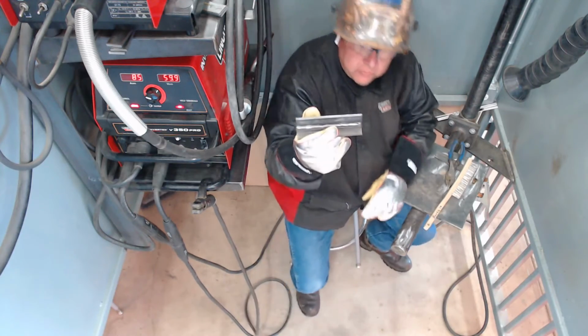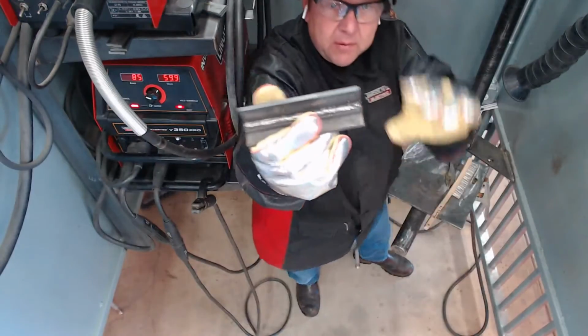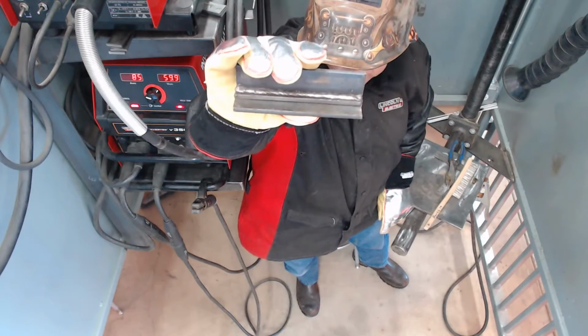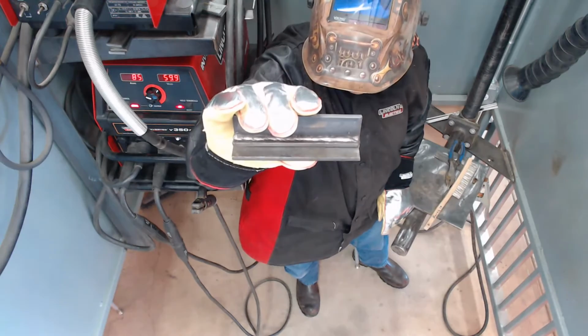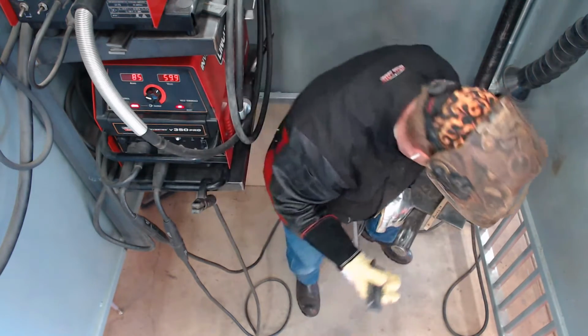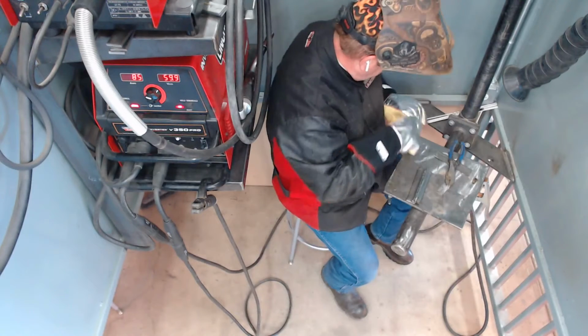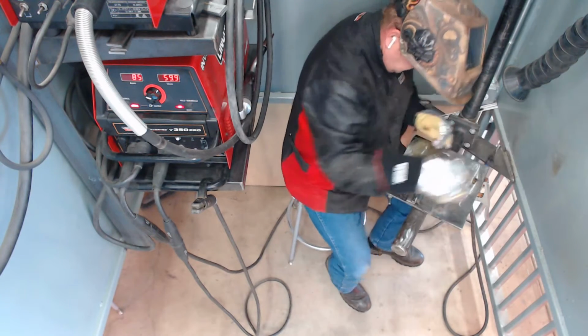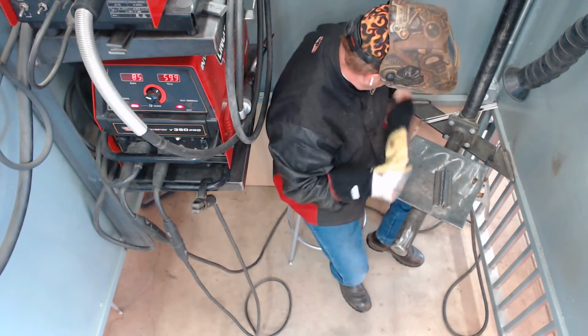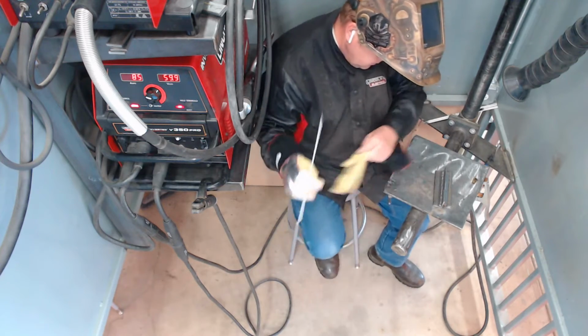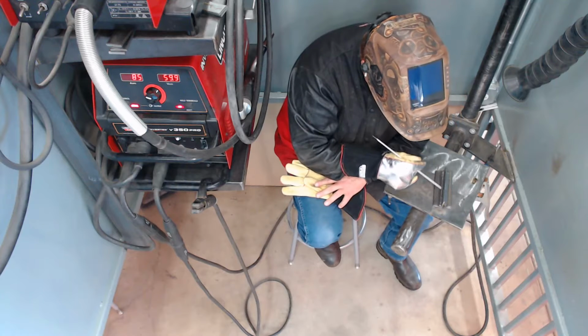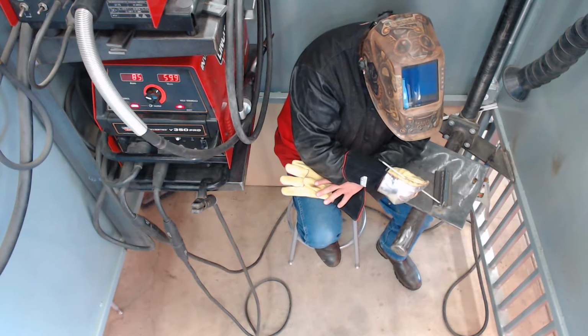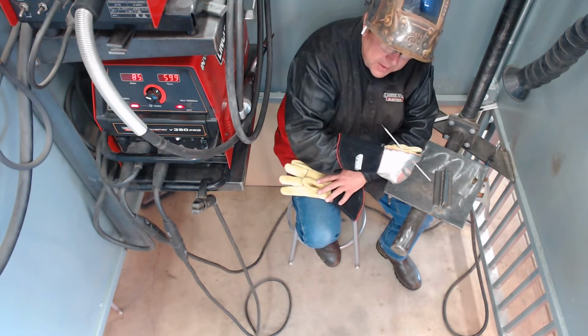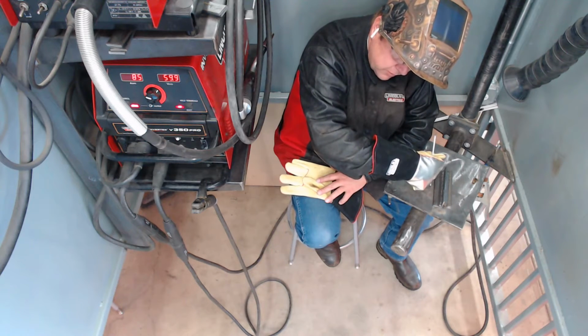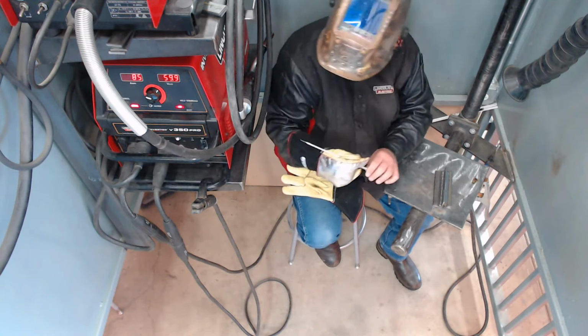Your first pass on this should be relatively flat. Get my big fat finger out of the way there so you can see it. That's pretty much what it should look like on your first pass. Right? However, if I can see where the metal is joining to the bottom piece of metal, then that tells me you were too far out. And that's a weak spot in that metal.